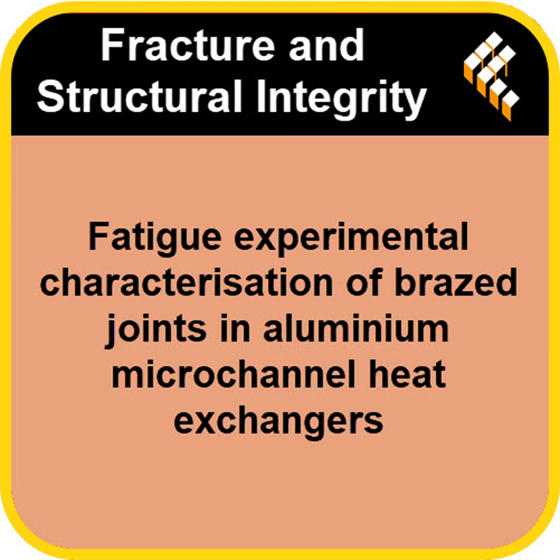And did the model clearly point to one specific location? Absolutely, without a doubt. The simulation showed a critical concentration of tensile stress, pulling stress, right at that theoretical sharp edge, specifically at the toe of the brazed fillet, and even more specifically along the lateral edge of the MPE tube. Okay, so not just anywhere on the toe, but on the side edge of the tube where it meets the fillet. Precisely. This finding was crucial because it told them exactly where to focus their subsequent fatigue tests.